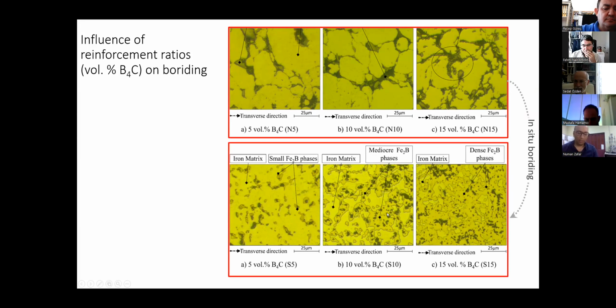It is very relieving to see that there are not any other phases. For example, if you have an iron boride and a higher iron boride phase at the same time, you will clearly see the difference because of the tone of the color after the etching. We see only a single color for iron borides and a background, we see iron matrix.